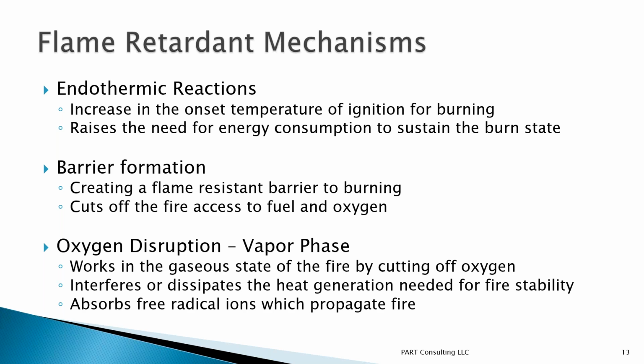Endothermic reactions basically raise the energy consumption needed to sustain the burn state. Barriers are just simply that: when a flame gets started, the decomposition immediately creates a flame-resistant barrier. And oxygen disruption, your halogens are here. They basically react in the vapor phase, and it cuts off the oxygen, and it also interferes with the heat generation needed for fire stability. It's because it absorbs the free radical ions, which propagate the fire.